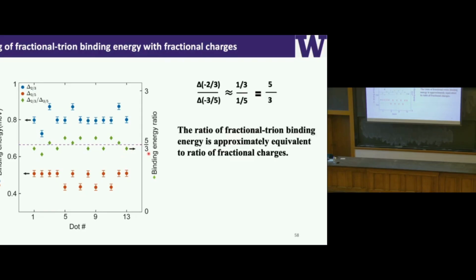So the take-home message is that the ratio of the binding energy of the 2/3 state to the 3/5 state is equivalent to the ratio of the fractional charge, 1/3 to 1/5. So that's our strongest evidence that we can read out the fractional charge using this optical spectroscopy technique.